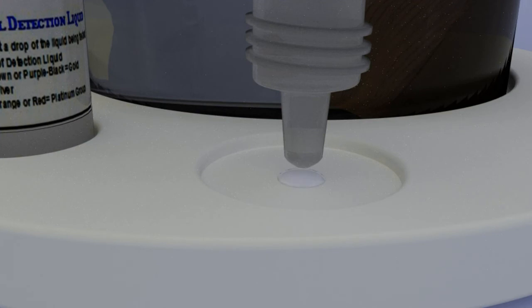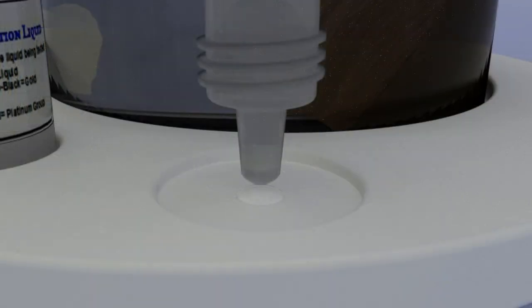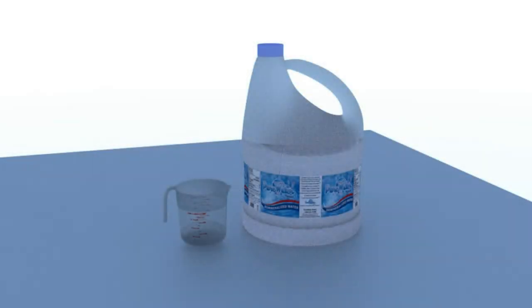This test will ensure that no dissolved impurities will remain clinging to your gold mud. If you see any change in color, even the palest shade of blue, then rinse again with water, and repeat the ammonia test. When the test results are negative, that is, when no color change occurs, your gold will be at least 99.95% pure. Give the gold mud a final rinse with about a cup of distilled water.